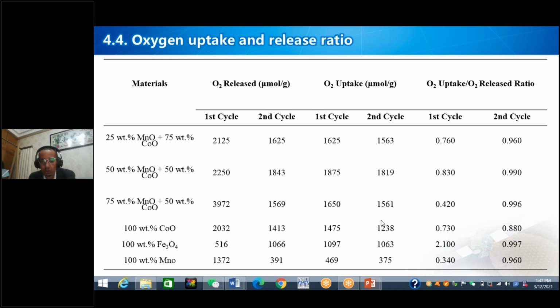Okay, so for example, when you think of pure manganese oxide, in the first cycle 0.34 is very poor. In the second, it is higher. When you think of iron, it is just higher in the first, and in the second also higher. But the main thing is that iron is the main part, but we need the supporting material. Later we are going to prepare real material with cobalt and manganese as the supporting material.